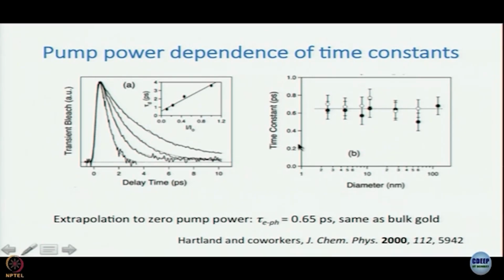And then the interesting thing that they showed here is that this time constant they got when they plotted against diameter, and again this is a semi-log plot where the x axis is logarithmic, so that they can show data from say 3 nanometer all the way to 120 nanometer. The time constant remains exactly the same irrespective of the size of the nanoparticle. Okay. This is one thing.